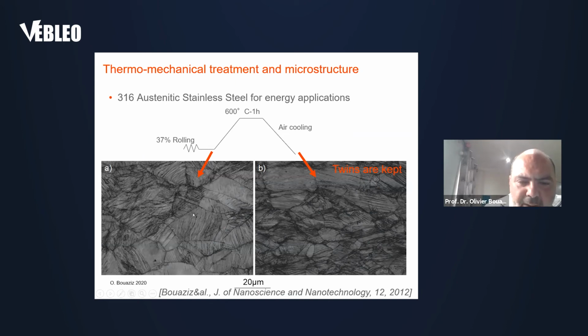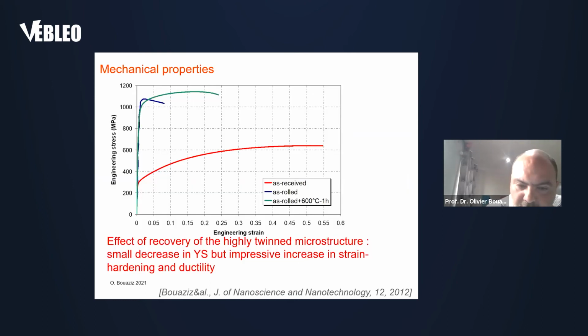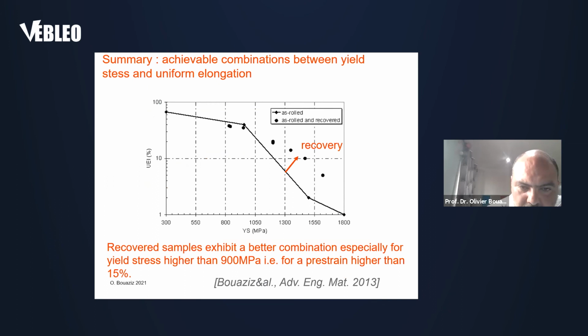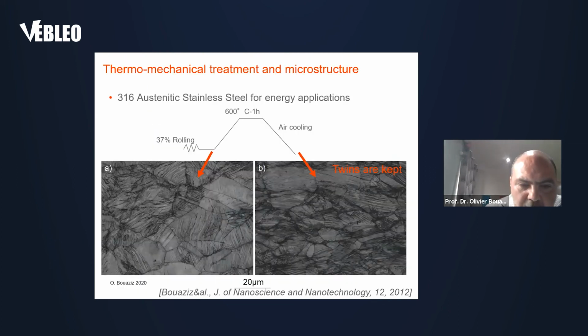By ASTAR ACOM map, you see that after the recovery treatment, all the twins induced mechanically during the rolling are kept in the structure. So the structure is very dense in twins. And so it is a kind of nanostructured material because the interspacing distance is very low.